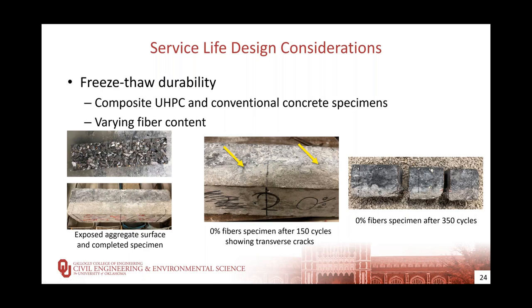These composite specimens were then subjected to the ASTM C666 testing protocol. A 0% fiber specimen is shown here because it was the only fiber percentage to show damage in the UHPC, and for these specimens, the damage consisted of transverse cracks across the entire specimen shown here after 150 cycles and at the end of the test.